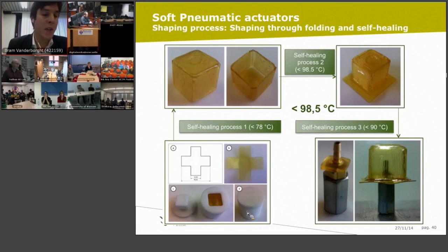So what we do in order to produce such a pneumatic cell, because first we developed only a pneumatic cell instead of a complete muscle, we started from a cross, cut from a sheet of this self-healing material. Then we put it in a Teflon mold, and then we used the self-healing properties, so we put it in a furnace, in order to produce one part where all the edges are connected. Then we used the other, stiffer material for the lower part, and then we added a little tube in order to pressurize this cell.